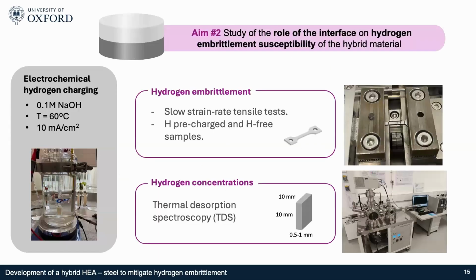So then for the second part, we started with putting hydrogen into the samples. We did electrochemical hydrogen charging at 60 degrees, because the idea was to introduce hydrogen into the high entropy alloy, the hybrid and the steel. Then after charging, we did slow strain rate tensile tests and thermal desorption spectroscopy to measure the hydrogen concentrations.